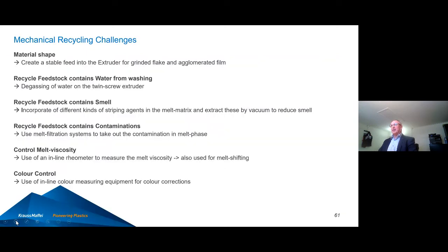So mechanical recycling challenges we have seen over, let's say, the last 15 years. First was to change the shape. We have flake, grinded flake, we have films. So the grinded flake with a bulk density of 0.3, 0.35, that's easy to feed in the extruder. But nevertheless, the extruder needed to be adapted to that. Then we have agglomerated films, so the very thin films Jan was talking about. We get them washed, we get them cleaned, and then we make an agglomeration step to allow them to be fed into the extruder as well as possible, in line with cutter compactors. And we have a cutter compactor being equipped directly for a twin screw extruder, so different from what others do.